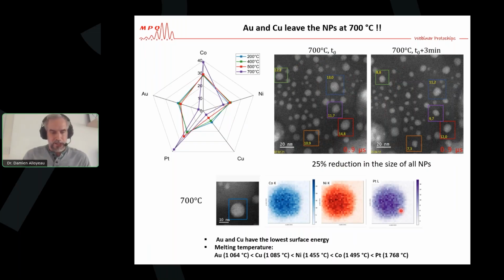And when you look at the numbers now, if you want to understand what's going on, the first thing you look at in the system is the surface energy. And it turns out that gold and copper have the lowest surface energy. So it makes sense: if you want to minimize the energy of the system, those two metals have to go to the surface. If you look at the melting temperature, gold and copper have the lowest melting temperature. And we know from other experiments that gold-copper nanoparticles, if they are small, evaporate at 700 degrees under the vacuum of the microscope. So this experiment makes sense.